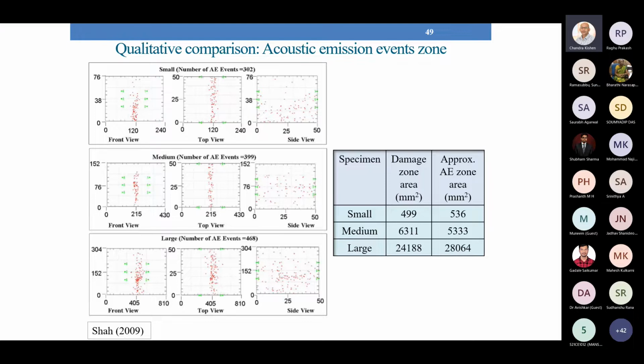So for small, medium, and large size specimens, we have the acoustic emission events. We have computed the size of the fracture process zone. So we know the damage zone, and using the energy equivalence, we could obtain a very close match between what we obtained from acoustic emission and through energy equivalence.